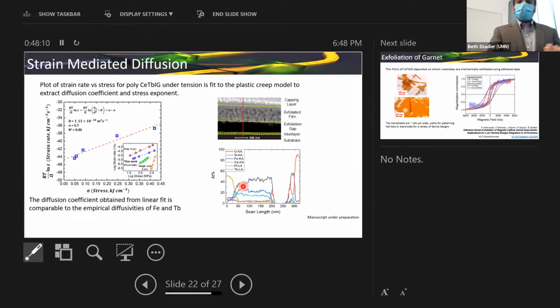Next, we take a cross-section TEM image of these films, where we see that we indeed have that exfoliation gap a couple of nanometers into the film from the interface. When we do a line scan using EDS, we are able to see that perfect exfoliation gap, and on either side of it you have the elements we are looking for.